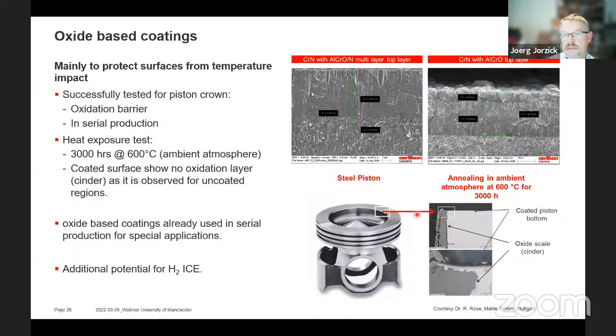And here the issue is, and this is a kind of test we did together with one of our customers, Mahle, where the piston crown was coated, and then this piston was put into an annealing ambient atmosphere at 600 degrees C for 3000 hours. And in the area where the coating was applied, you see that there's no oxide layer building up, but the other uncoated area show how the oxide layer is being built. And that again gives a good example or shows nicely how those quite thin coatings can even protect the parts against a high temperature impact.